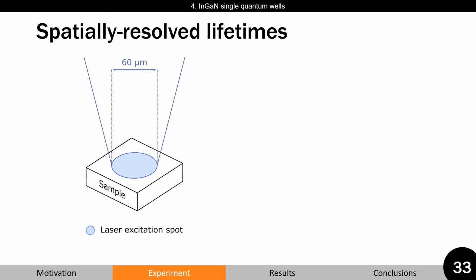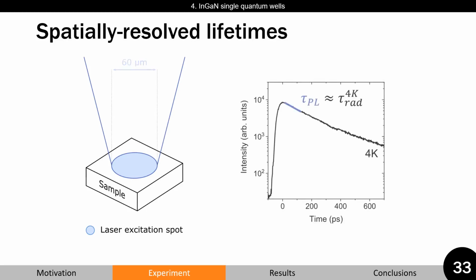The laser beam is focused on the sample, and then photoluminescence transients are measured at low temperatures. For samples with low defects, at low temperatures, one can assume that within the first picoseconds, recombination is purely radiative.